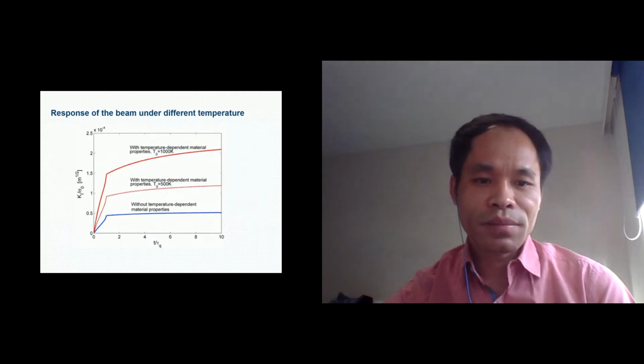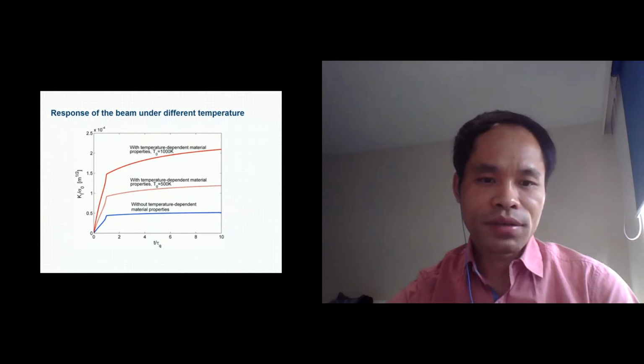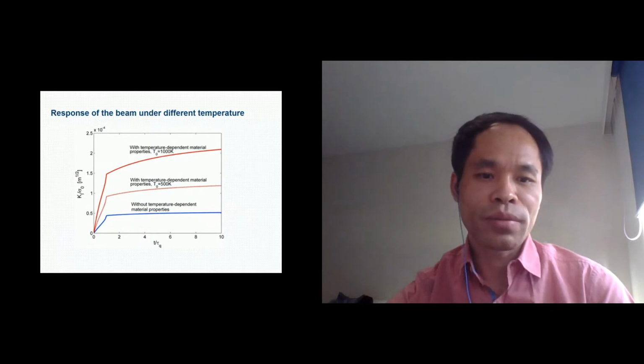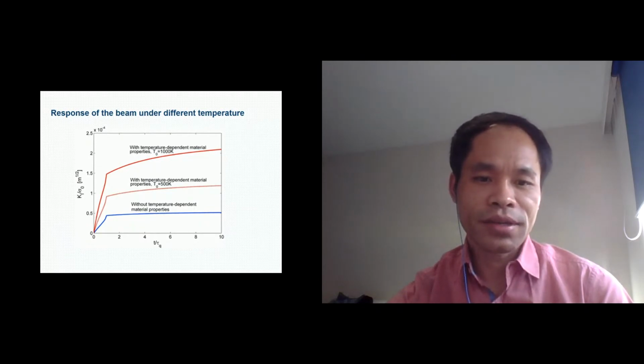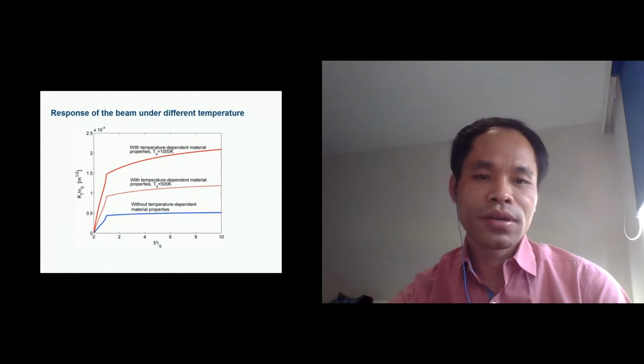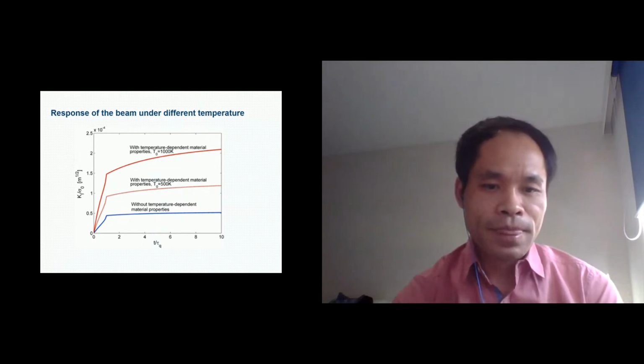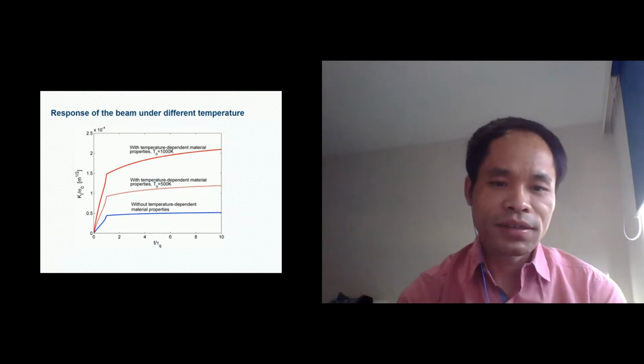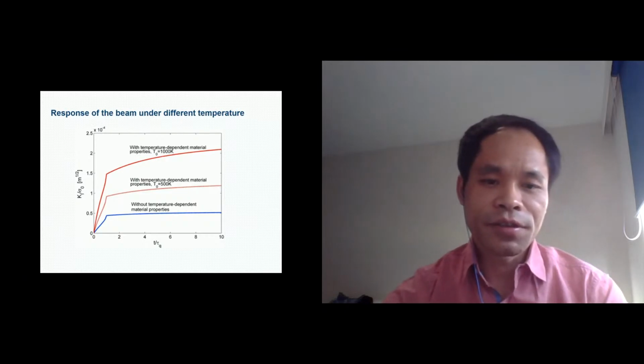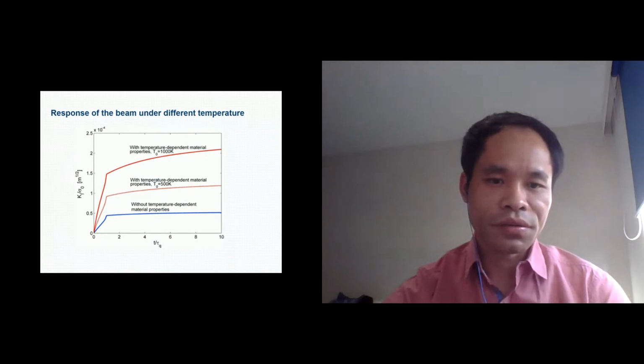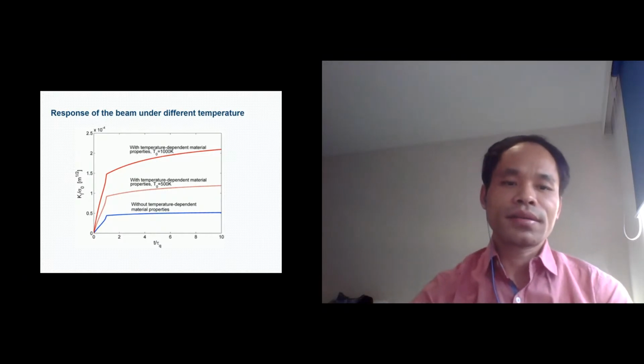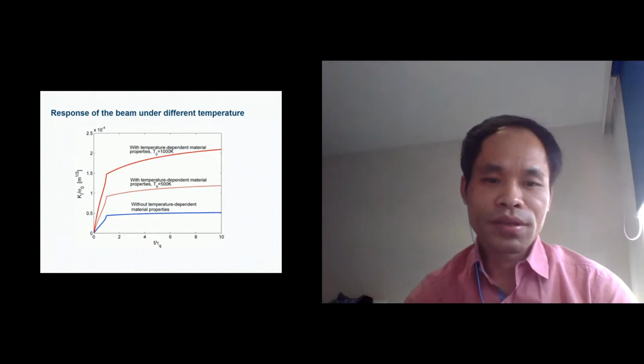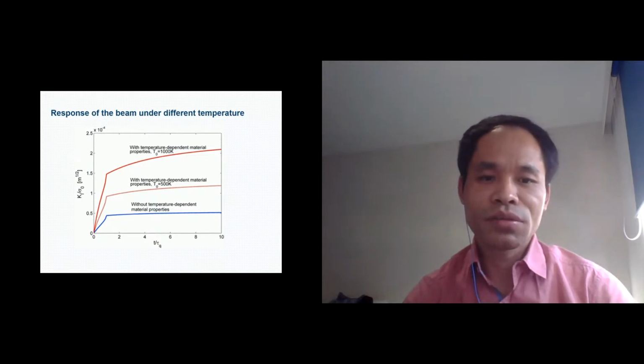Here, according to them, when you consider temperature, the stress intensity factors keep moving higher. But without heat conduction, you will see the value is low. So when you apply different temperatures, you will get a different value for the stress intensity factor, which is a function of crack growth. That is why people try to introduce temperature along with crack propagation instead of utilizing only the basic fundamental models.